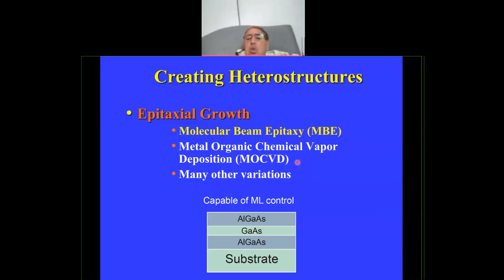But in the other technique, they use all kinds of chemicals. For example, for arsenic they use arsine, and for gallium they use metal organic gallium, and so on. So this is mainly chemical, and this is mainly solid. And this is what you do practically. Because these are very thin layers, you use a substrate, and then you deposit layer by layer, whatever you like, according to the design and device you aim to achieve.